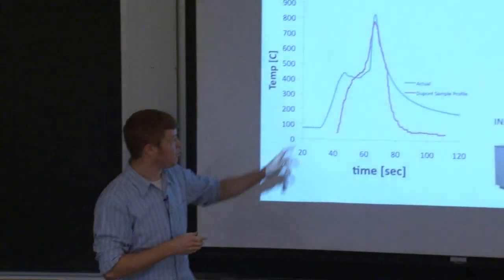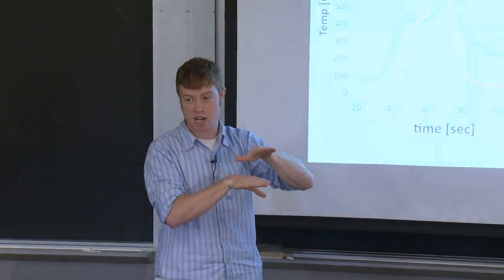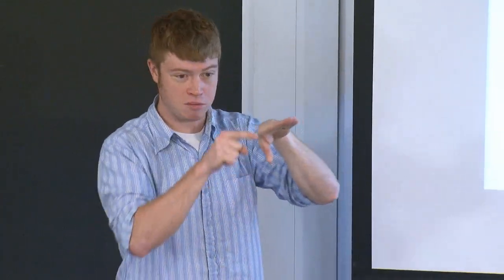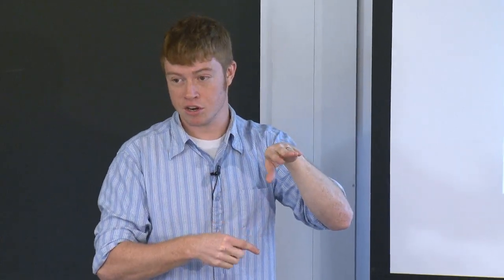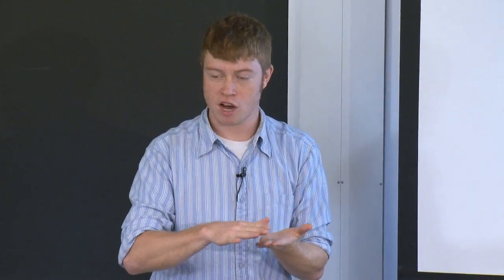And some of the ways they actually figure out the actual profile underneath the contacts, versus you measuring the temperature on the side of the contact, actually touching the silicon or the silicon nitride surface, is you actually measure hydrogen diffusion underneath it. And so they'll actually etch off the contacts and measure, using secondary ion mass spectroscopy, the hydrogen concentration off the contact and underneath the contact, and it'll actually tell you what temperature it saw based on that diffusion profile. So there is some good science going on, but there's not a lot of great papers on it.